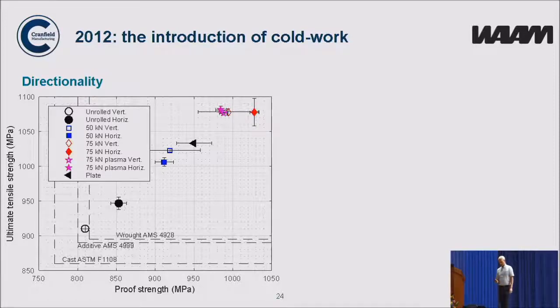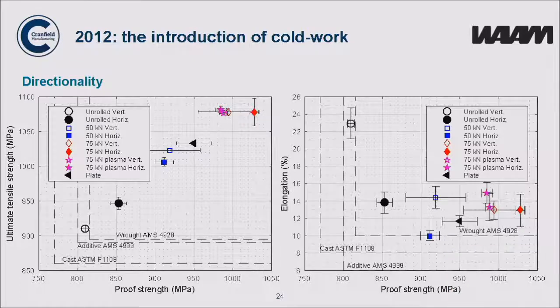And as I mentioned, it's fully isotropic. And if you look at the elongation, you can see that we now have an elongation of around 13%. So this material is actually much better than the material they're currently using. So we're offering them, by them I mean the aerospace industry, better properties, shorter lead times and lower cost. So as you could imagine, they're pretty interested in this.